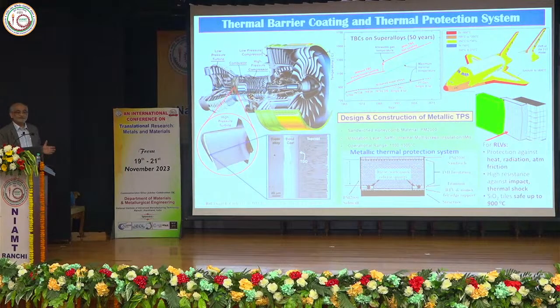Instead, if you can gradually build it, so you have 100% metal and finally 100% ceramic, with the composition varied every 10%, every 20% in between, the coefficient of thermal expansion mismatch will be minimized. As a result, you get both: a metallic structure for toughness and fabricability, and thermal protection from the ceramic.